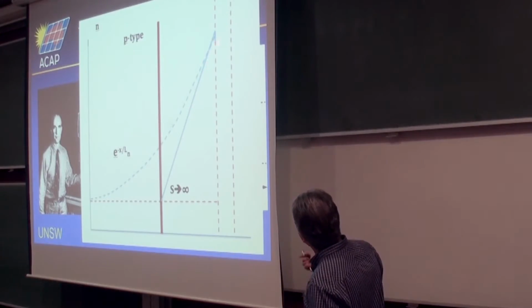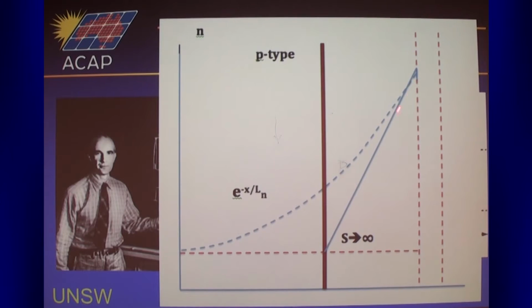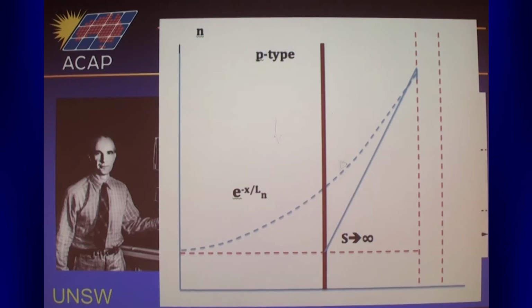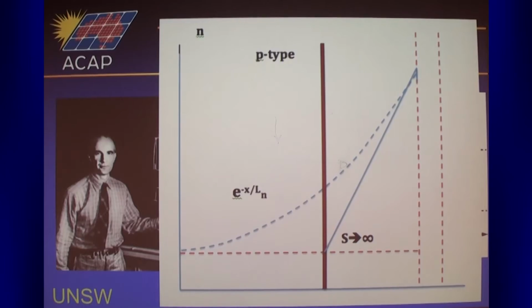So what's that do? You can see that, wow, you've increased the gradient here. So you're getting more current associated with that. So that dark knee voltage is moving in, so that's going the wrong direction. So you don't want infinite surface recombination velocity if you want a high open circuit voltage solar cell. And remembering that as the design was evolving, this thickness here was reducing. So going from the conventional space cell to the violet cell, this thickness was substantially reduced.